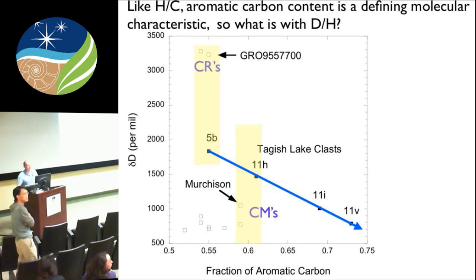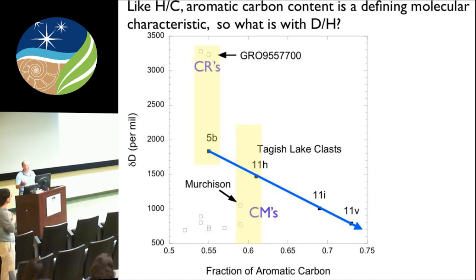Are there alternative ideas of how those interesting morphologies that you said were from spinodal decomposition and the glass transition could be created at below 50 Kelvin, really low temperature? People make spherules. So I don't know how to put a temperature on it. There's a paper that Larry showed me where people make these little spherules in a plasma with benzene. That's hardly low temperature. Yeah, that was a very high temperature.